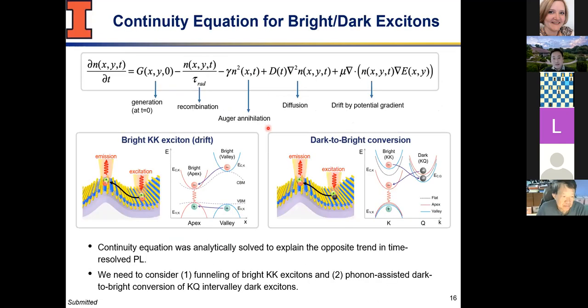So we decided to think about a model, and that really helped us predict and at the same time understand our results better. Here I'm showing an equation. It's really nothing but a continuity equation of the density of excitons. That's my N. I have a generation term, which is my input photon energy. And some of them will recombine and be emitted, so you have a radiative recombination term. And you have another recombination that is not radiative. These are thermalization processes, like annihilation. So basically, this takes away density of excitons. And typically, if you look at the literature, that's about what you consider.